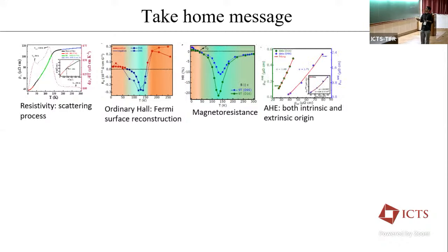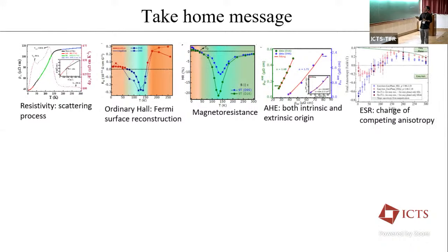And also we say that anomalous Hall effect has both intrinsic and extrinsic origin, which are dominant in this material. And then ESR measurement says that there is a change of competing anisotropy, and the spin reorientation is nothing but a competition between shape anisotropy and the magnetocrystalline anisotropy.